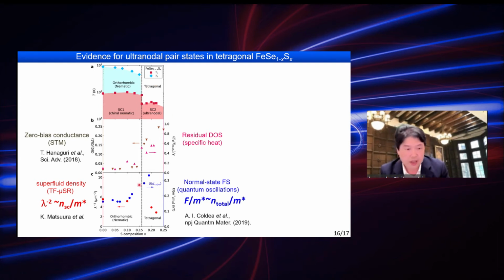And finally, we have also measured the transverse field μSR measurement, from which we can extract the superfluid density, 1 over lambda squared. Lambda is the penetration depth. And 1 over lambda squared is basically looking at the superconducting electron density divided by the effective mass, m star.